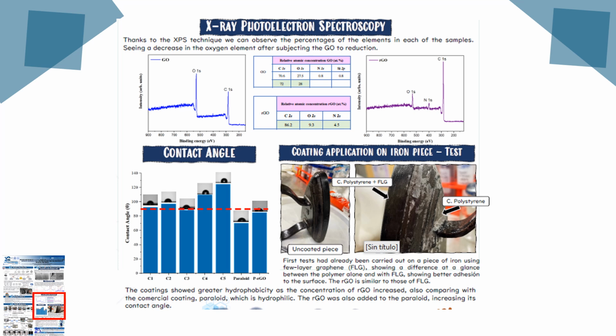Two, why is there more adhesion here and not in the sample sheets? Mainly it is due to mechanical anchoring. The sheet has been used for many years and its surface has been eroded over time, while the sample sheets are relatively new and have a very smooth surface. This conclusion we discovered with roughness measurements.